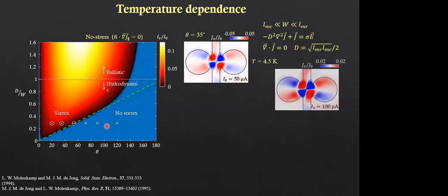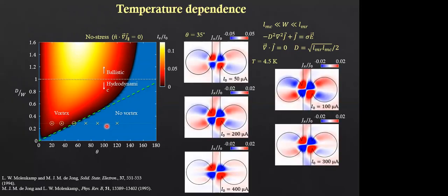Okay, let me just go slightly faster here. So what we can do to prove that it's okay: already we have proven using two data points, two sort of arguments, that this is a hydrodynamic flow. First of all, the angle at which the vortex to laminar transition happens is low. And second, we observe a two vortex state in the chamber. So that already proves that we are in the hydrodynamic regime. We can look for more signatures.